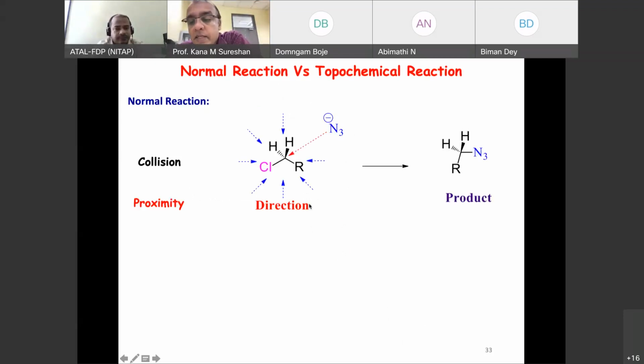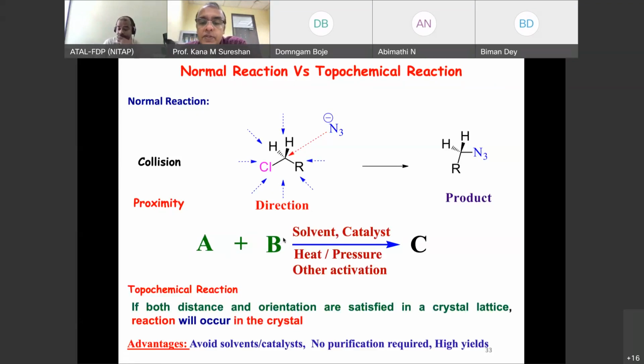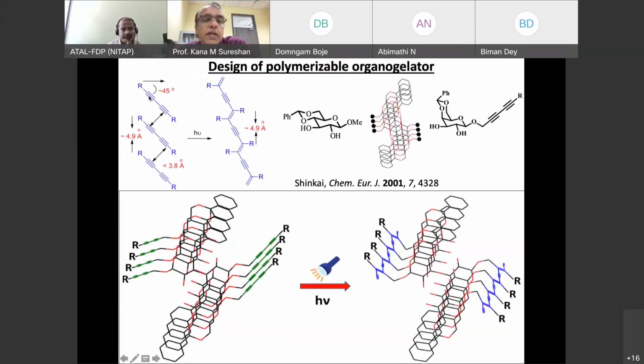Topochemical reaction is a reaction in the crystal or in a self-assembled state. It's not in an isotropic solution where you need a solvent. There is no solvent required. It is in the crystal and it's due to proximity. If the reacting groups are in proximity, they will react on their own or with some mild activation. If they are assembled like this at this distance, about 5 angstrom between the monomer units, and at this angle, 45 degrees to the normal, they will undergo this kind of 1,4 polymerization. What you get is a fully conjugated ene-yne polymer, which is conducting. It's called PDA, polydiacetylene. This is a conducting polymer.